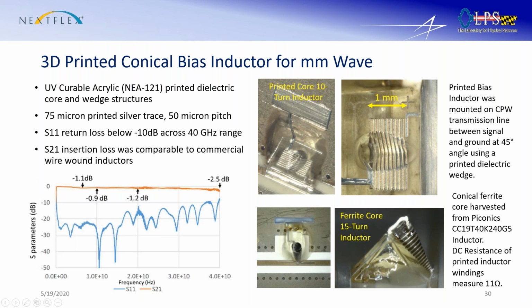low frequency end up. When we did this, we actually got performance on par with the packaged device that's about 10 times bigger than this. This shows the S parameters. The insertion loss at 40 gigahertz was minus 2.5, which was excellent. And the return loss was well below the minus 10 where we want to see it. It starts peaking up around 40 gigahertz, the other end of the spectrum. But these were really nice results, comparable to the SMT device.